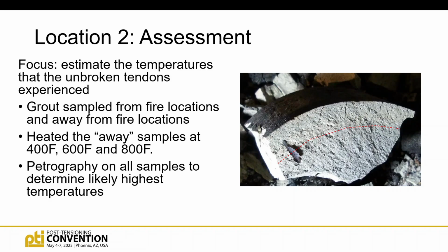Here's a shot of the grout, and if we had a darker room, it would show up. This area is nice and gray, but above this red line, and that's about 3/8 of an inch, it was more of a buff color. There was definitely a color change in the grout where it was affected by the heat, which you would expect to see. But it's different than concrete, right? Because concrete, when it's exposed to heat, typically it's the aggregates that change color. And I'll show you a slide of what that looks like.